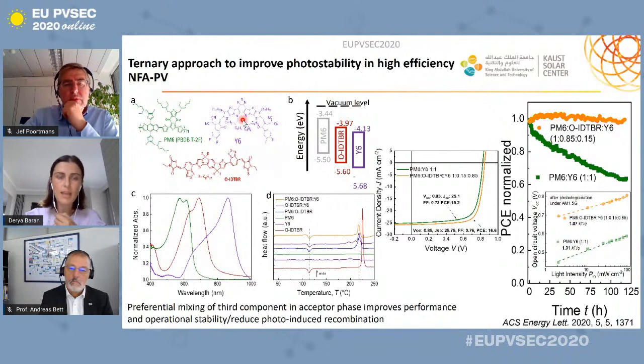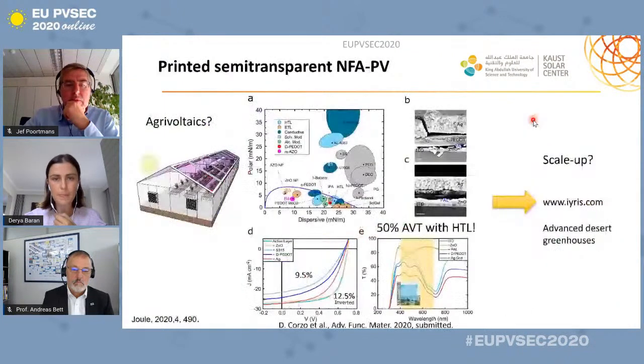And in this particular blend, we improved the efficiency up to 16.6%. And not only efficiency, in this case we have observed that the photostability of this blend, that is known as unstable, is improved dramatically while we are reducing the photo-induced traps in the binary system.